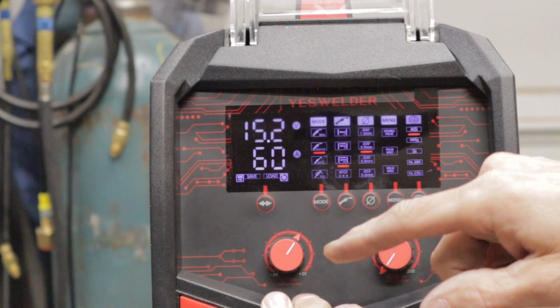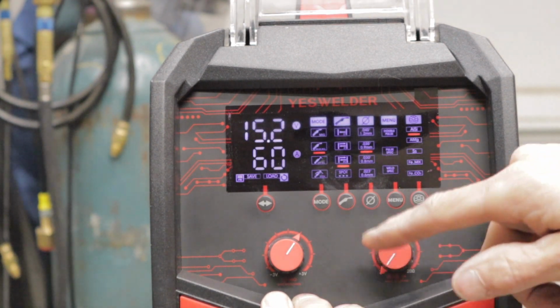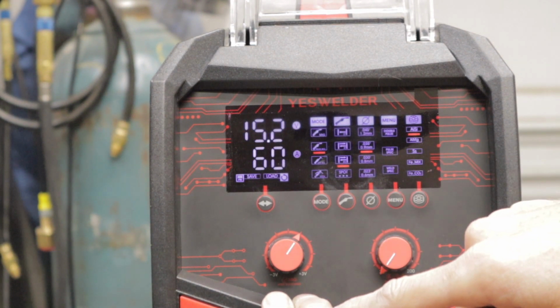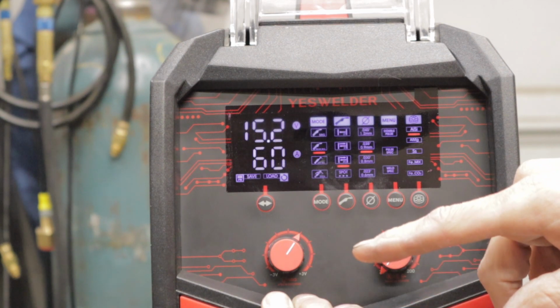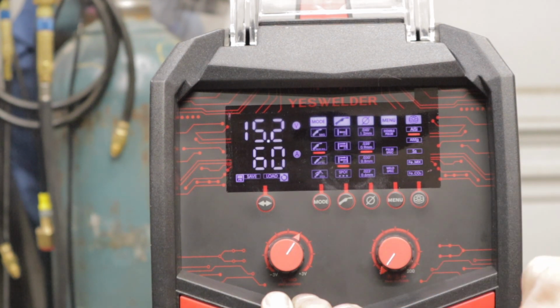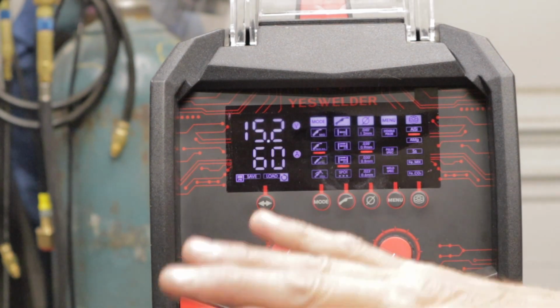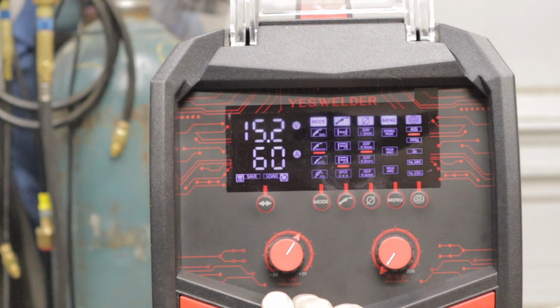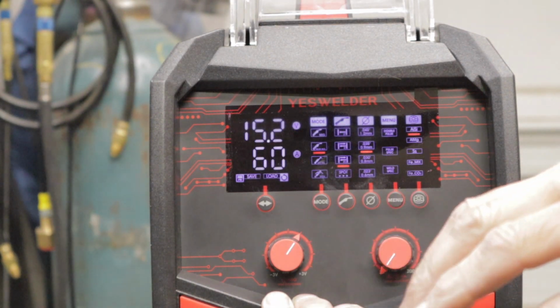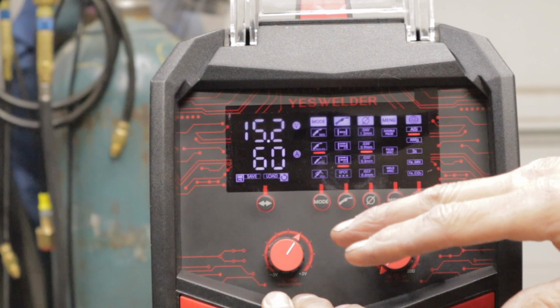And so you either have to come back after you've done that and weld a spot at the beginning of the weld, and at the other end of the weld it's usually gone concave at that point, and you now have a big crater at the end of your weld because the heat has built up so much.